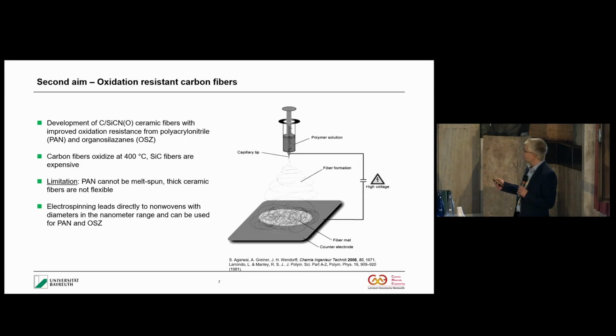Here, for example, we process the fibers by electrospinning. So we also have people here who like electrospinning a lot. We have a polymer solution, then we have an electric field, the solvent is evaporating, and then the fiber forms. Actually it's not a ceramic fiber, it's a polymer fiber, because later on you have a pyrolysis step for the ceramization. In this case, we use polyacrylonitrile and organosilazanes as the polymers, and they form a copolymer, and then we have these kinds of non-wovens.